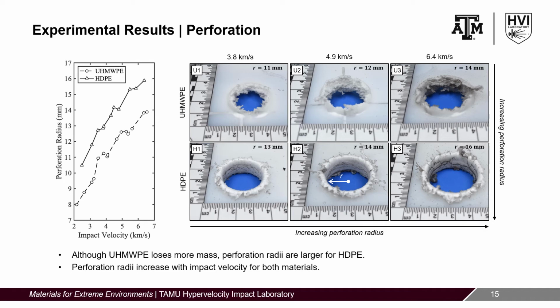This increase in hole diameter is likely due to the apparent melting behavior resulting from adiabatic heating and thermal softening in HDPE. High-density polyethylene specimens seem to melt even after the projectile has completely perforated, resulting in residual plastic hole enlargement. This feature is not evident in ultra-high molecular weight polyethylene. This notion further validates the claim that the higher mass loss seen from ultra-high molecular weight polyethylene experiments is attributed to its brittle-like response, while high-density polyethylene conserves more of its mass through large-scale deformation.